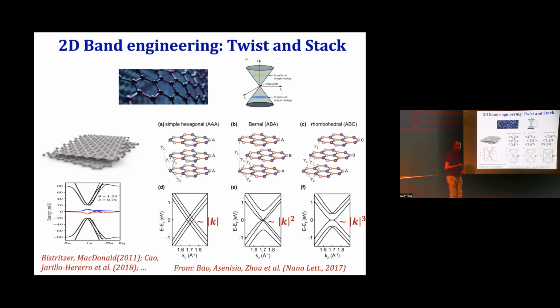Are these stacks only up to three, or do they continue beyond? It continues. It turns out that it's rhombohedral stacking. You can continue: A, B, C, A, or any number of layers. In the simplest model, you just get k to the power n. Now there are effects beyond the simplest model that would split this a little bit apart. It's not actually k to the n down to the lowest energies, but you do get a very, very flat dispersion.